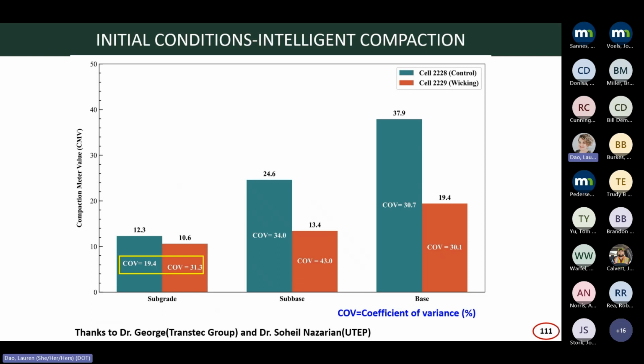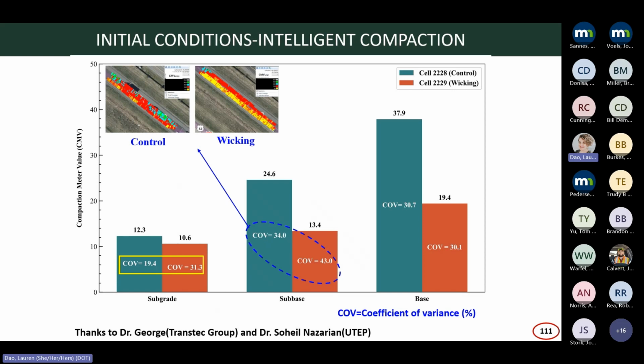So we see a variation of around 11% between these two test sections, with a coefficient of variance of 19% and 31% in the wicking section. So that's actually contributing to the subbase. Also, there was a rainfall event during the construction of the wicking. So all these factors, as you can see in the intelligent compaction mapping, in the control section there is more uniformity in the color.